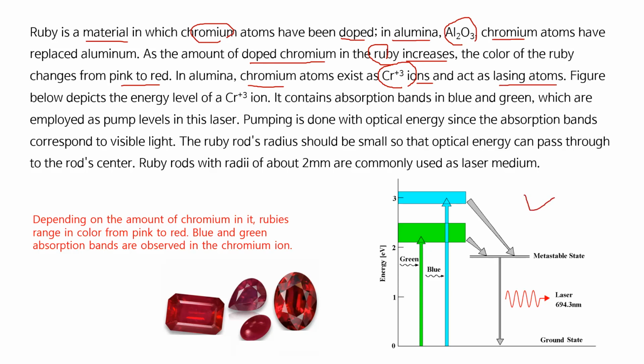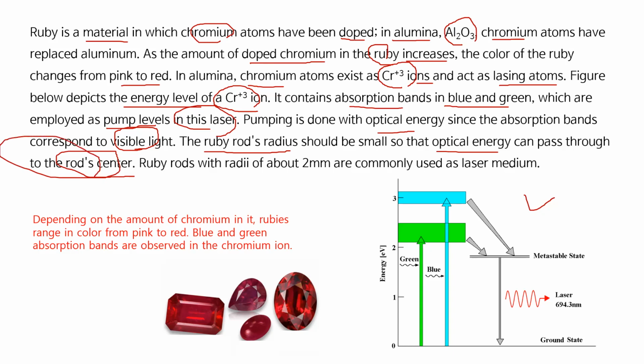This figure depicts the energy levels of the chrome plus 3 ion. It contains absorption bands in blue and green, which are employed as pump levels in this laser. Pumping is done with optical energy since the absorption bands correspond to visible light. The ruby radius should be small so that optical energy can pass through the rod center. Ruby rods with a radius of about 2 mm are commonly used as a laser medium.